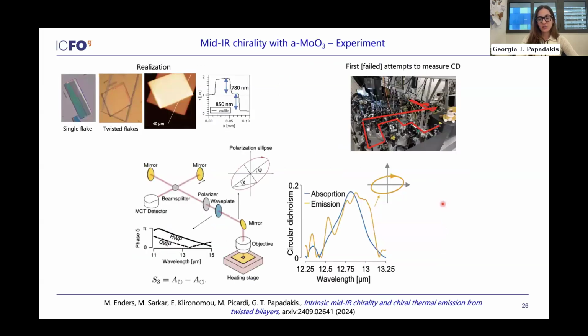So the next thing we did is we actually built this. So we started with a single flake, and then we exfoliated a second flake and carefully placed it on top of the first flake. And here's an AFM picture of that. So these are not very thin flakes. We don't need thin flakes in the mid-IR. And once we had our device, then we had to characterize it. And of course, this took a very long time because, as I said in the previous part of the talk, phase retarders don't exist in the mid-IR. So we needed a quarter wave plate in order to generate circularly polarized light in order to characterize chirality. But we didn't have that because it's simply very difficult to purchase commercially.